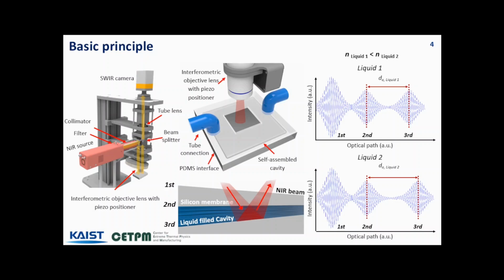Using the near-infrared interferometer, we perform a vertical piezo scan within the liquid-filled channel to capture the interference patterns. The distance between the first and second interference patterns remains constant as it is determined by the silicon thin film. However, the distance between the second and third interference patterns varies depending on the liquid filling the cavity. From these patterns, we extract the refractive index by measuring the optical depth between interfaces at a specific point.